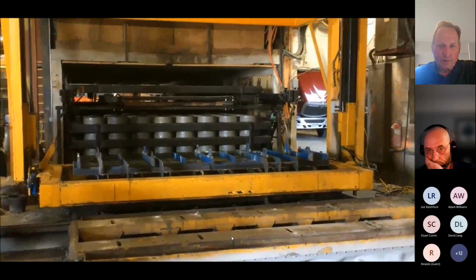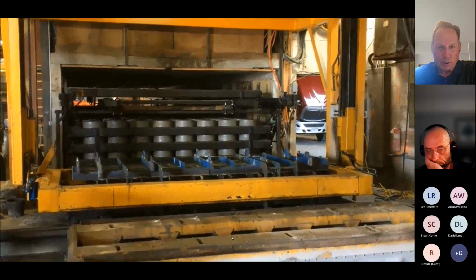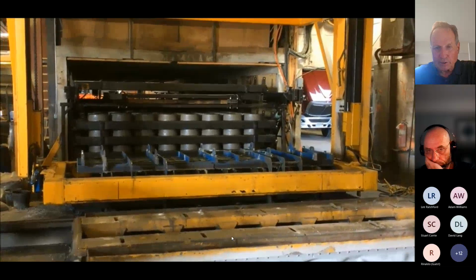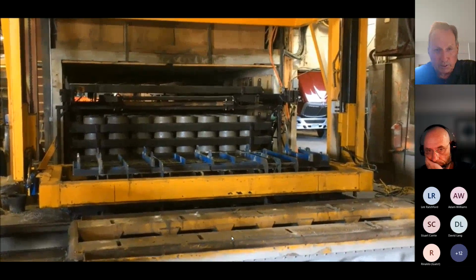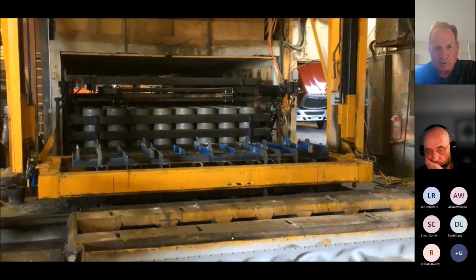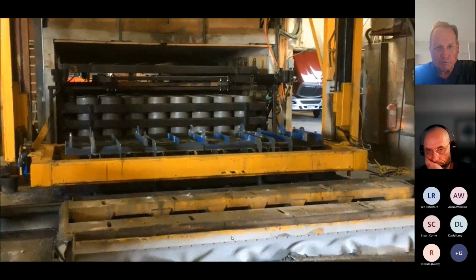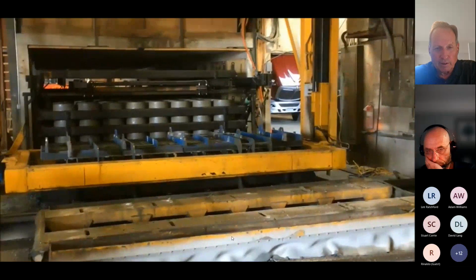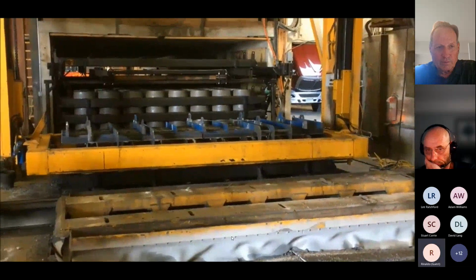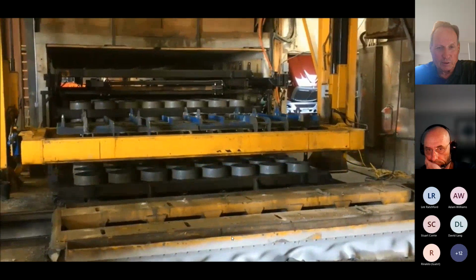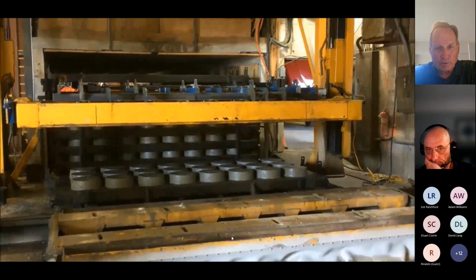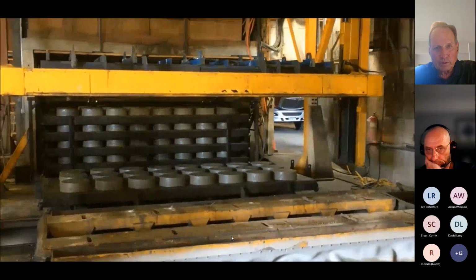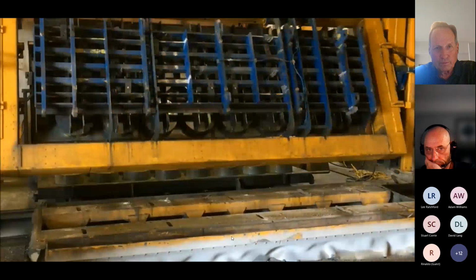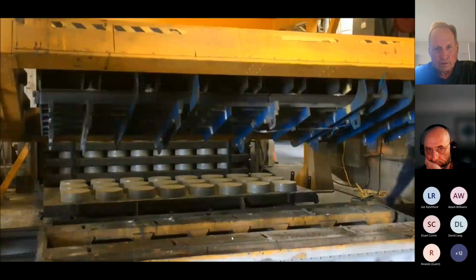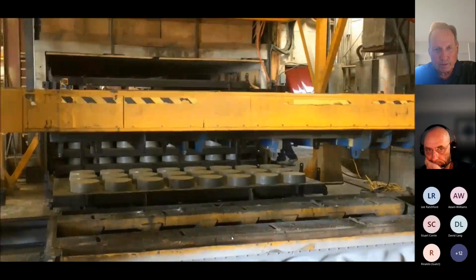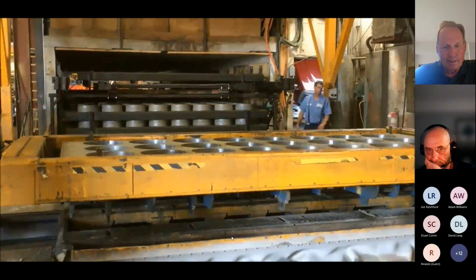And then when he sets it down, now there's a few seconds here where compressed air is being introduced into the mold on what's now the top surface. That's to break the suction that's created when you had it the other way and vibrated all that concrete in there. And then it'll start lifting slowly, and then once it knows it's released, it'll go quicker. It's a little herky-jerky, but...